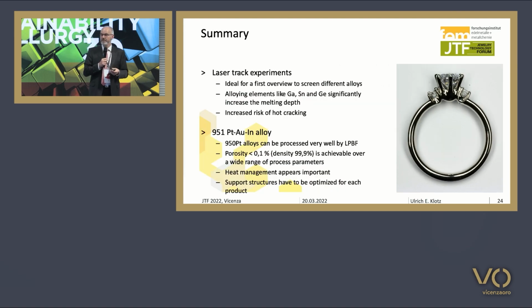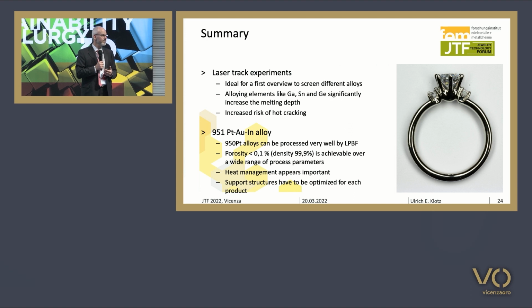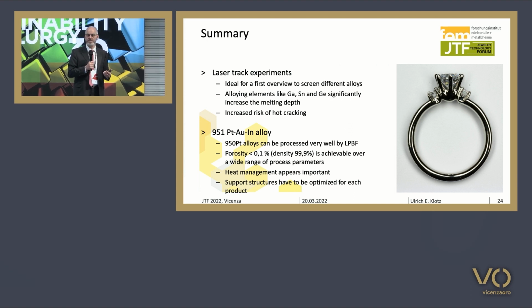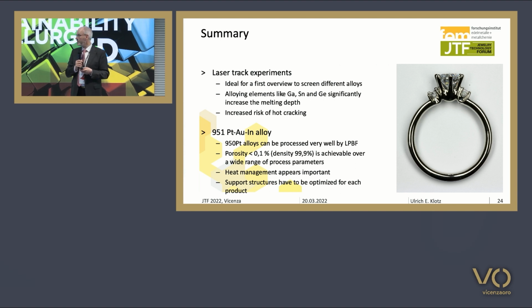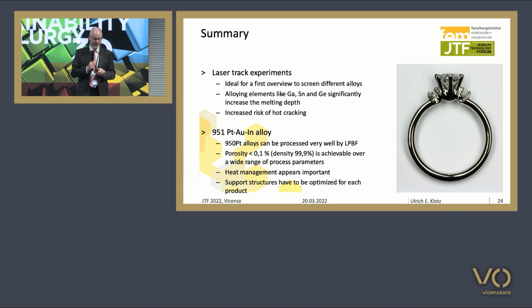Now let me summarize my presentation. Such laser track experiments are good to easily evaluate the effect of alloying elements, because you can easily prepare them and not much material and effort is needed. We see that some elements are critical. Gallium, tin, germanium, they increase the melting depth. They are critical in terms of hot cracking.